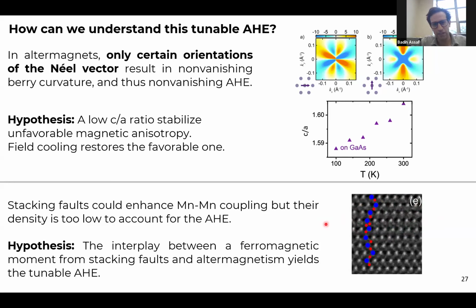I want to highlight here that the density of these stacking faults is still really low to account for the strength of the anomalous Hall effect, and that magnetometry on manganese telluride grown on gallium arsenide was still yielding moments that are on the same order of magnitude as I showed you earlier, 10 to the minus 2 to 10 to the minus 3 Bohr magnetons.